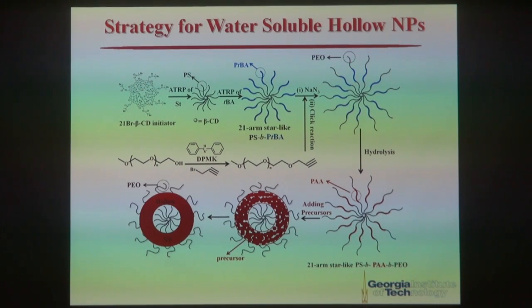Once you have this tri-block copolymer in hand, you do the hydrolysis, converting this blue block into the red block, that is hydrophilic PAA. Adding precursors, you get hollow nanoparticles capped with PEO. To get this star-like tri-block copolymer, we do sequential atom transfer polymerization of styrene and tert-butyl acrylate, then convert this terminal bromine group into azide functionality by reacting with sodium azide. On the other hand, we prepare this alkyne-terminated PEO. Do the click reaction, and you get this ABC star-like tri-block copolymer.